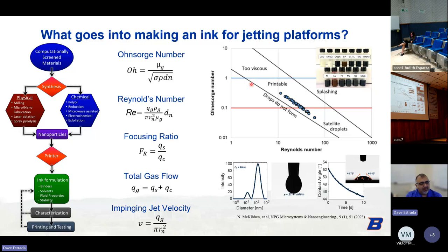And so we really want to be within this printable window, which is about 0.1 to 1 on the Ohnesorge number and about 2 to 100 on the Reynolds number. These data are just out of my team, showing that we can tune our co-solvent vehicles for these nanoparticles in and outside of that printable window. And here's our library of inks, showing that we can do everything from oxides and 2D materials to different metals. We do a lot of characterization in this process through dynamic light scattering to look at the hydrodynamic size of the particle in solution, and then surface tension through pendant drop and contact angle to see how it interacts with the substrate.